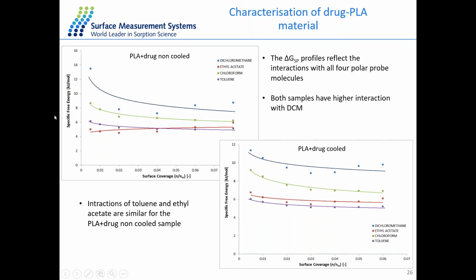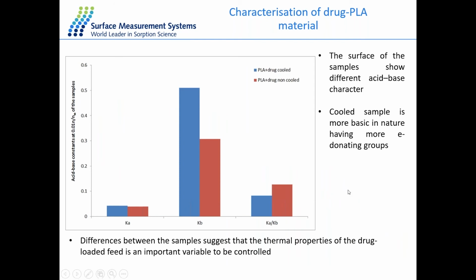What we've also then gone and done is calculate the specific free energy. So we've injected dichloromethane, ethyl acetate, chloroform, and toluene in this case. And what you can see is the interaction of our non-cooled material and our cooled material with all these probe molecules. For both samples, the dichloromethane has a much stronger interaction with the samples. In this case, what we can understand from this is that there must be some labile functional groups on the surface of the samples that are responsible for a stronger interaction with dichloromethane.